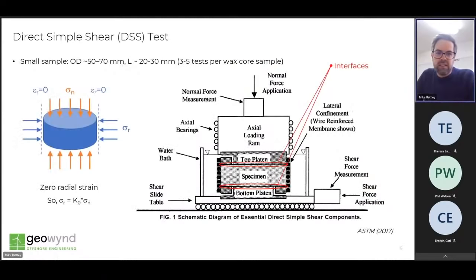So the DSS test is performed on a short cylindrical test specimen with a diameter typically between 50 and 70 millimetres and a length between 20 and 30 millimetres. It's therefore possible to obtain a few such specimens from a single wax core of an intact sample taken offshore.